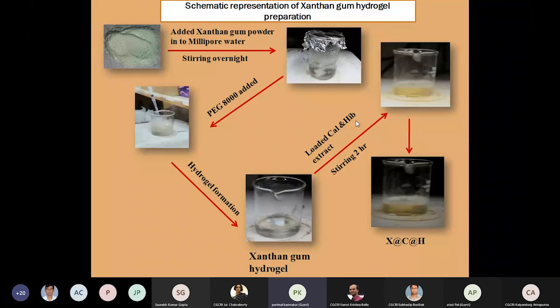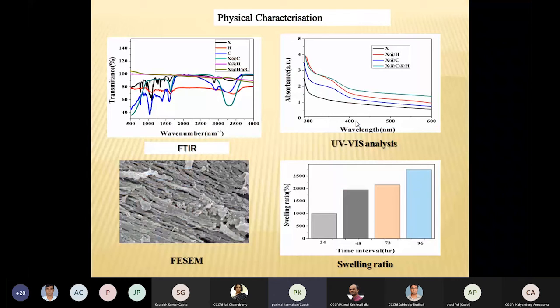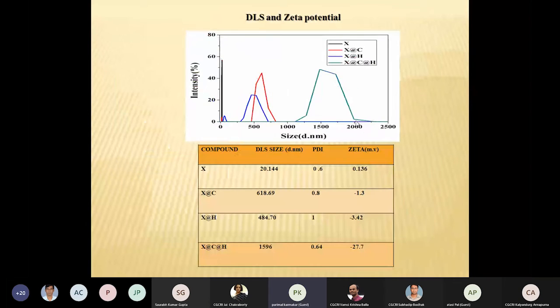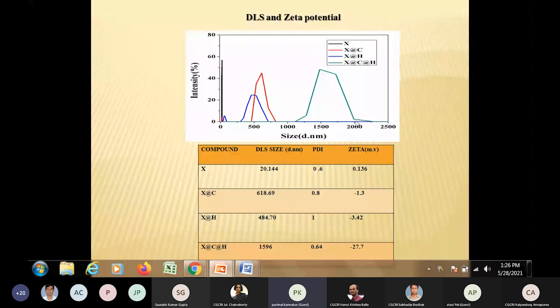But now, because the wound healing process is a multi-step process, and each of the steps involves the response of different cells, a single agent may not be sufficient to heal the wound, particularly a chronic wound. So we have to add different kinds of excipients. In this case, we use two excipients, hibiscus and calendula, where we have checked their loading using FTIR and UV analysis, and their swelling ratio is also determined, and SEM analysis showed a matrix-like structure, and their zeta potential is also estimated, so that they have been loaded with both calendula and hibiscus extract.